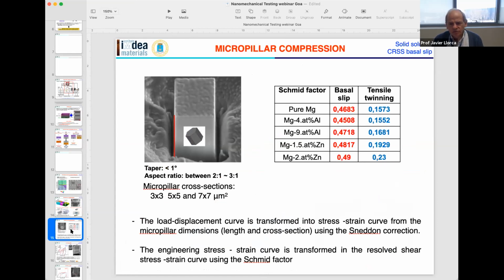The first challenge is to try to study or to measure what is the critical resolved shear stress for basal slip in a material that is a magnesium aluminum alloy or a magnesium zinc alloy with different aluminum or zinc content. So this is the typical micropillar. We use micropillars with a square cross section. We have a lot of expertise in carving these micropillars, so you can see that the taper is very small. Tapering is normally below 1 degree. These are straight micropillars, and we have been able to carve micropillars, all of them with an aspect ratio between 2 to 1 or 3 to 1. This is to avoid buckling during compression.